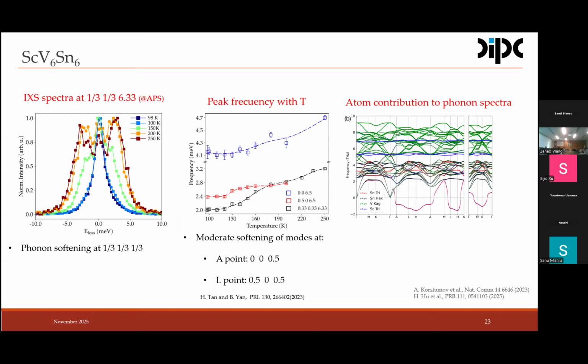It's actually a complete soft plane of phonons, which only collapses at the H point of the Brillouin zone, at the 1/3, 1/3, 1/2 critical wave vector. And this is indeed consistent with theoretical calculations that predict a nearly flat mode in the ALH plane with the minimum energy at the H point.